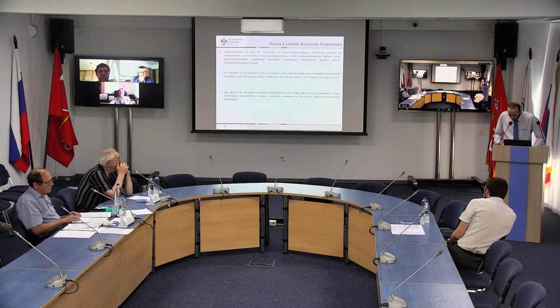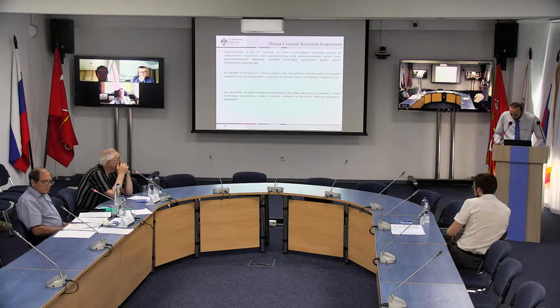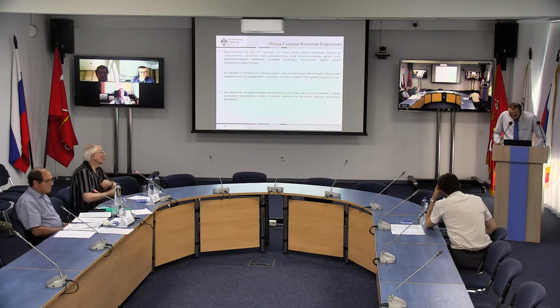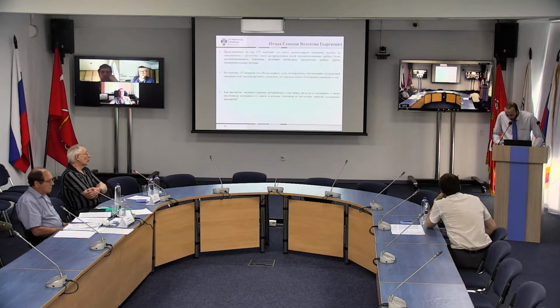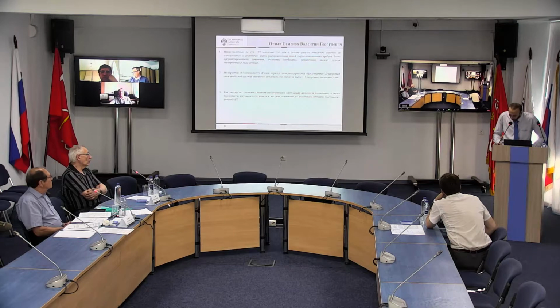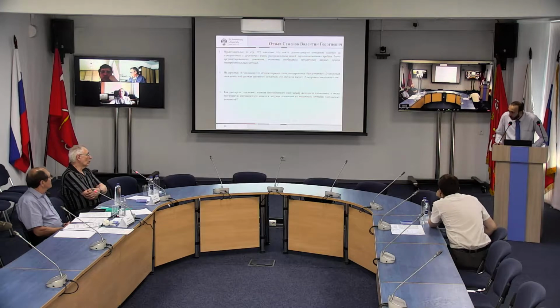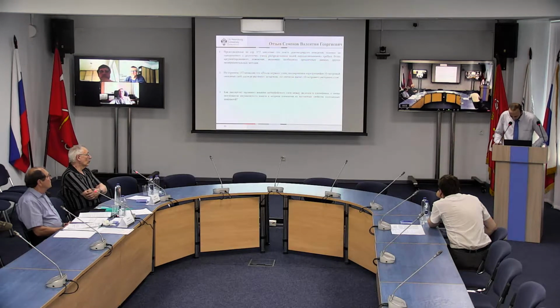The last comment was about the effect of interference between aluminum and iron nanowires and iron layers. I suppose that interference between these two materials could affect the crystalline direction of the deposited nanowire. So it may have an additional effect, besides the magnetocrystalline contribution, on magnetic behavior. Probably that's one of the reasons why we have high texturing for these nanowire diameters. Additionally, it can contain some inhomogeneities which deviate the magnetic behavior of the nanowire from some average, leading to smearing in the FORC results. So that's all. Thank you.